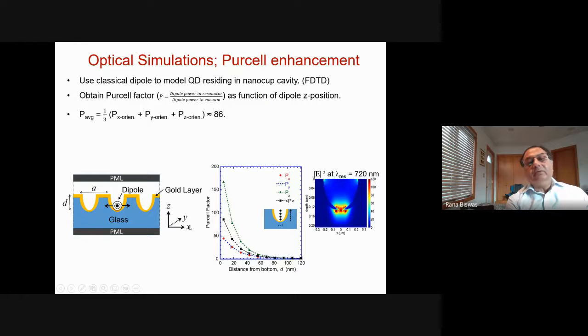So if you're very close to the bottom and you're looking at this region for small d, you want to average the X, Y, and the Z polarizations, and you get an average Purcell factor that's very high, you see 86 or so. But realistically, you have to look at all these different positions of the quantum dot or dipole. So once it sits quite a bit above the bottom of the cup, then the Purcell factor, of course, goes down.